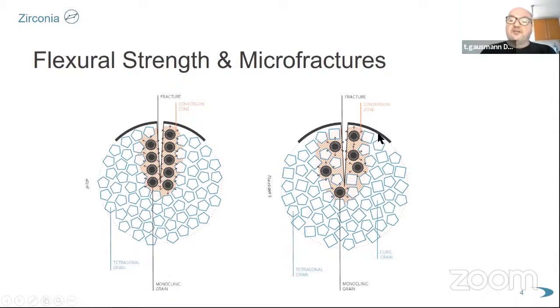Here you've got a material that is like a 1000 megapascal material. The 1000 megapascal material is a mix between tetragonal and cubic. And you can clearly see that along this crack, you don't have that many tetragonal crystals any longer that can be changed. So the cubic can't change from cubic to monoclinic. So it can't compress the crack. So the crack stop function in this material, in these 1000 megapascal or less, or cubic's got only 600 megapascal, is always weaker. Therefore, it's much more translucent. So you always have to find a balance. But I will go later into the details of this.